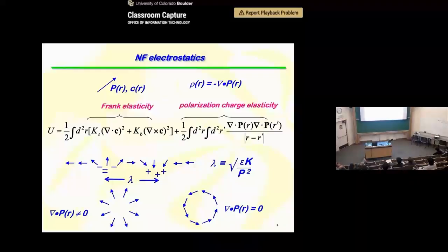So if you just had the typical liquid crystal elasticity, it just costs energy to produce a reorientation, a gradient in the orientation. So it would just want this gradient to get smaller and smaller. If you made this kind of deformation, it would just spread out basically to infinity. Okay, in the ferroelectric case, you have polarization splay, so that produces the opposite sign of space charge. So these charged sheets attract each other. So now this wall has an equilibrium width, which is this constant lambda. This is a trade-off between Frank elasticity and polarization charge. So this length is the square root of epsilon K over P squared. So the larger P is, the tighter this wall will end up.